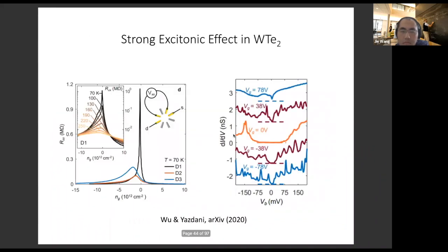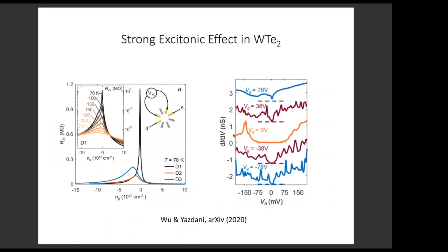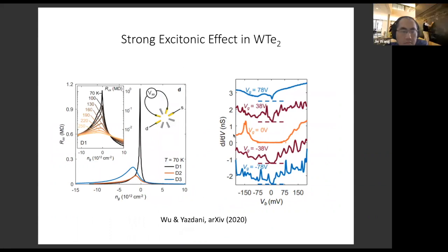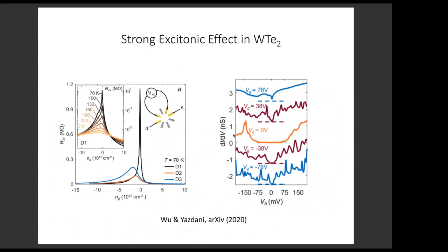So there are also some tentative reports. I think this is still something that needs to be digested. But there are at least some experiments saying that there may be some excitonic effects in tungsten ditelluride. The observed gap, both in transport and in STM tunneling, is much larger than what DFT theory predicts. So these were attributed to some kind of excitonic effects. So then the natural question is, we have an insulator with strong excitonic effects, meaning the interband renormalization is important. So then can our theory basically describe this WTe2? Our prediction is that it should be spin triplet.